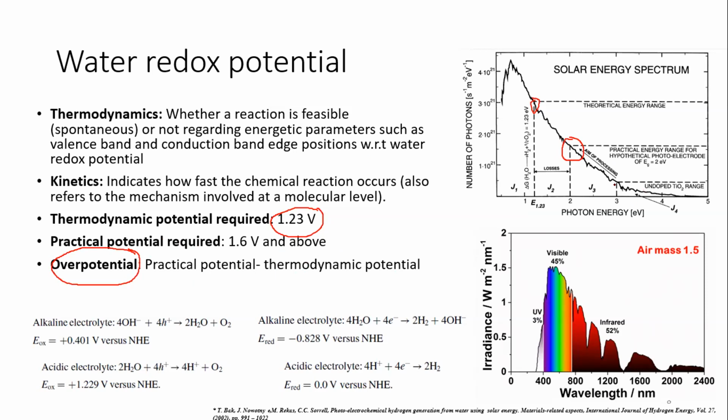If you look at the seminal work done by Fujishima and Honda with titanium dioxide as the semiconductor material, titanium dioxide is the best material for this water splitting reaction because it is chemically stable in different environments. But it has a band gap of about 3.2 electron volt. At 3.2 electron volt, the number of photons reaching this energy scale is very small, less than 3%.